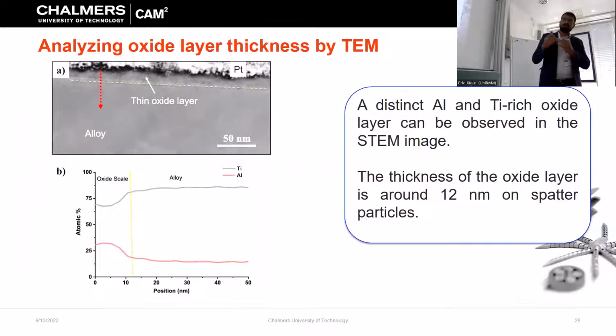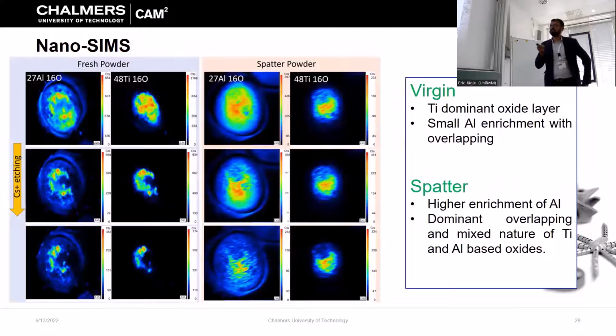Now the only question remaining was, if oxide is forming, is it a mixed oxide, a spinel type oxide? What is the nature of the oxide? That was complicated to analyze through XPS, so we did some NanoSIMS analysis, where we can see the aluminum oxide and titanium oxide and their location on the particle. From the location, we can see that aluminum and titanium do not have very similar locations, and aluminum is much lower compared to titanium in the case of fresh powder. There are some points where you can see mixed aluminum and titanium oxide formation, but in the case of sputters, it is a complete overlap. This means that in sputters we see a much more mixed type of oxide, as compared to the individual oxides in fresh powder.